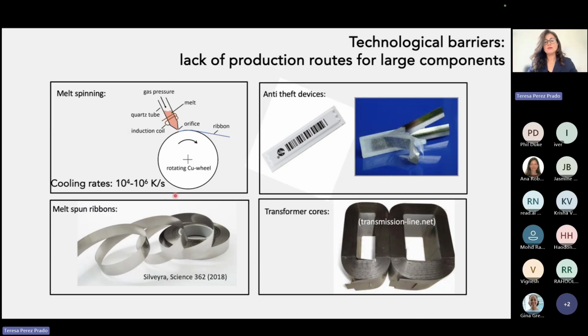It is possible, for example, using melt spinning. So we have here, for example, a container. This shaded area is the liquid metal. We apply a gas pressure, and then this liquid stream is ejected towards this rotating copper wheel. And in contact with this wheel, the material cools very, very fast. And then what we have is a ribbon, like the one you can see here. These ribbons are very thin, about 100, 200 microns. And therefore, yes, they are fully amorphous, because we are able to stabilize these disordered phases, but we cannot do much with them. So they have very, very niche applications. For example, they can be wound in some cases to make these transformer cores, but definitely we cannot make components. So we have here a set of extraordinary materials that we can, unfortunately, not use.